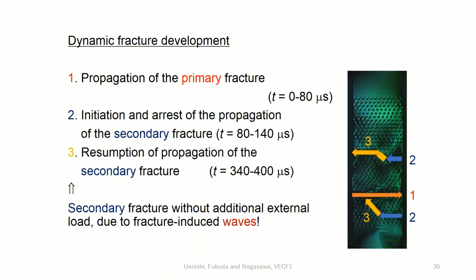Dynamic fracture development can be categorized into 3 stages. The first stage is propagation of the primary fracture, between time 0 and 80 microseconds. The second one is initiation and arrest of propagation of the secondary fracture, between time 80 and 140 microseconds. The last one is resumption of propagation of the secondary fracture, between time 340 and 400 microseconds. Obviously, the secondary fracture propagates even without additional external load. That is, its expansion is owing to fracture-induced waves.